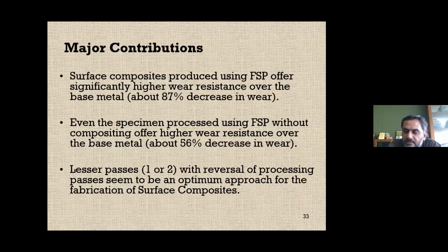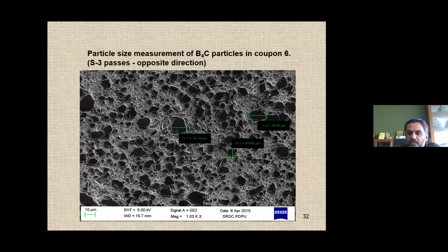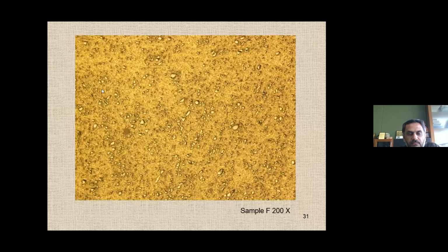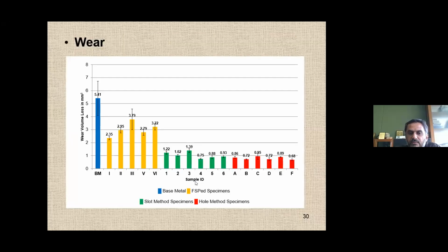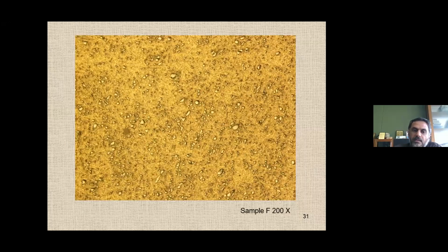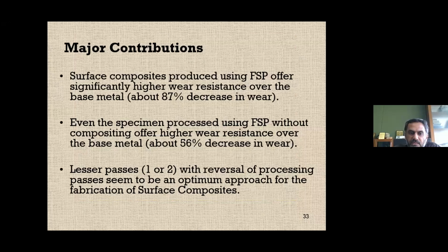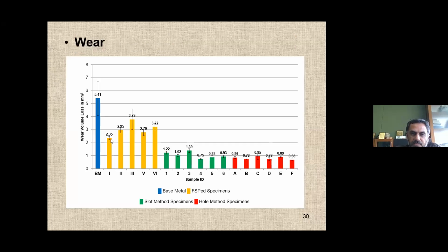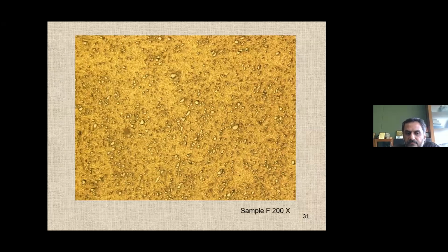So that was one case study. What is the outcome of this study? We found that the surface composite produced with FSP has significantly higher wear resistance over the base metal, 87%. When you compare the maximum of 0.95 with 5.4, that is around an 87% reduction in the wear. Even when you process the specimen with plain FSP without adding anything, there is a 56% reduction in the wear.